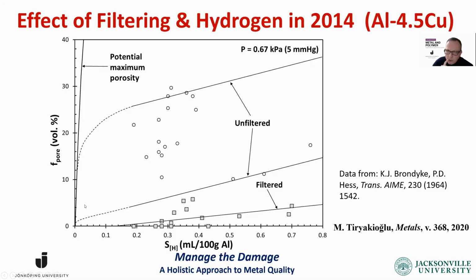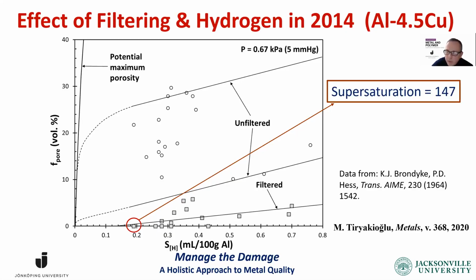But there are a couple points that I want to draw your attention to. First of all, let's look at this point, which is filtered, but it's lying on the x-axis, which means it has 0% porosity. Just to give you an idea, at this vacuum level, the supersaturation is 147, meaning that the specimen had 147 times the hydrogen solubility, the maximum hydrogen the solid could dissolve, and still no pores formed. 147 times, not 147%, 147 times what the solid could dissolve, and still no pores.